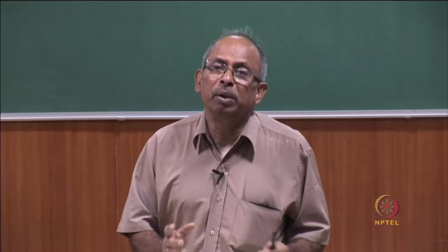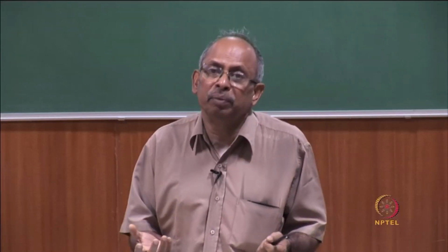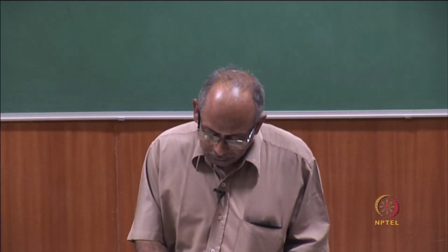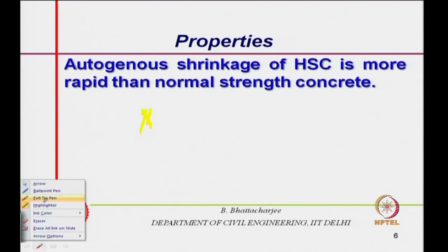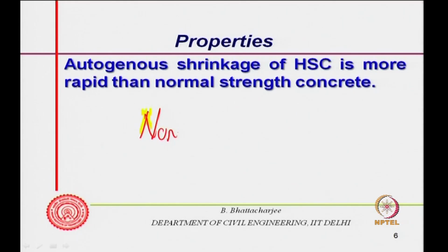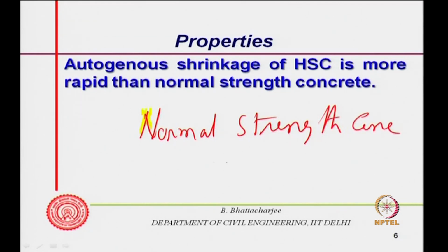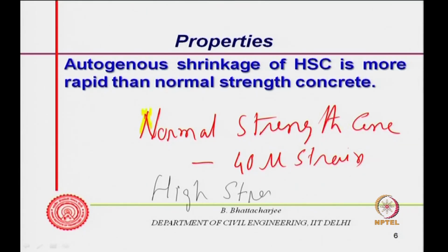During the time in which normal strength concrete may exhibit 40 microstrain, high strength concrete may show 100 microstrain at the same time.